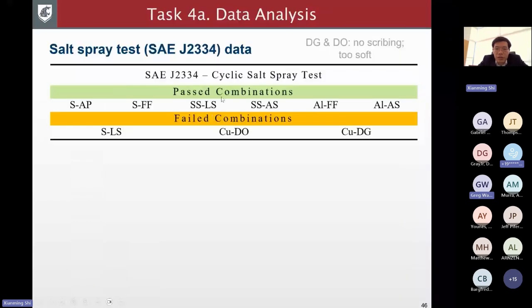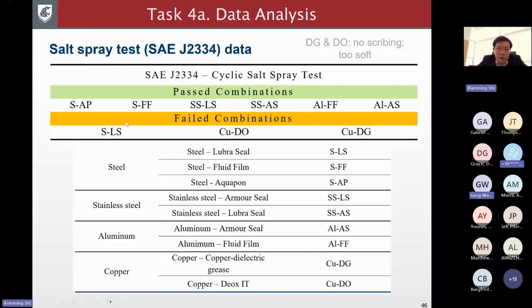Now, the good news is that for the cyclic salt spray test, most of the coatings pass the test. What that means is by the end of 60 cycles, which is equivalent to 5 years in the field, they do really well. In other words, you don't even need to reapply them every 5 years. Of course, in practice, most agencies end up reapplying them every 3 to 5 years just to be safe. But there are a few samples that failed the 5-year test.